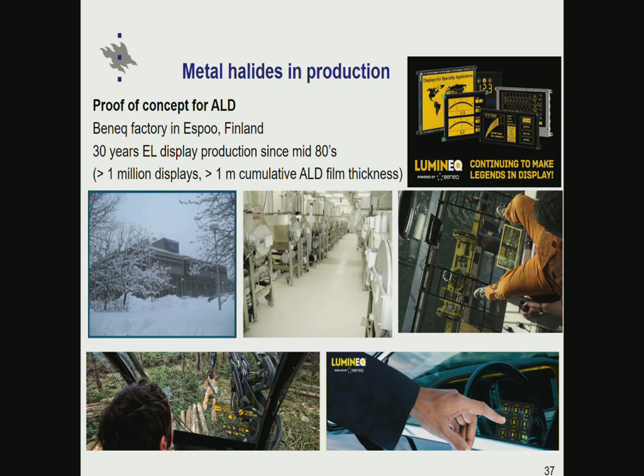Quite several years ago already, they exceeded 1 million displays produced. And there was a talk about how slowly ALD films are growing, so I calculated off the top of my head the cumulative film thickness. If you pile all these 1 million displays together, you have more than 1 meter thick layer of film. On the other hand, if you calculate the volume based on the assumptions I rapidly made, I came up with 30 liters of material. So this company has been in operation 30 years and they have produced 3 buckets of solid material only. And they are still doing good business.